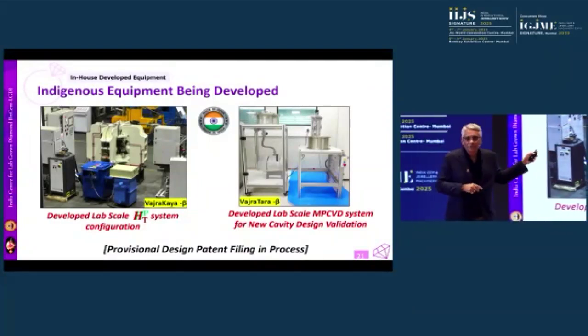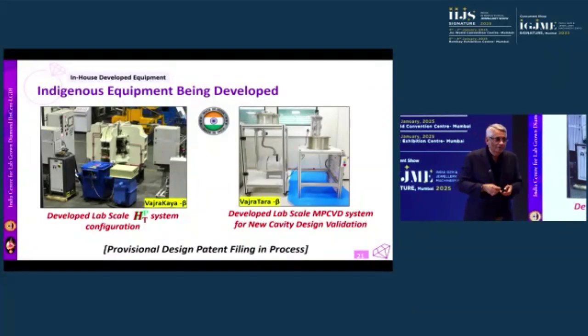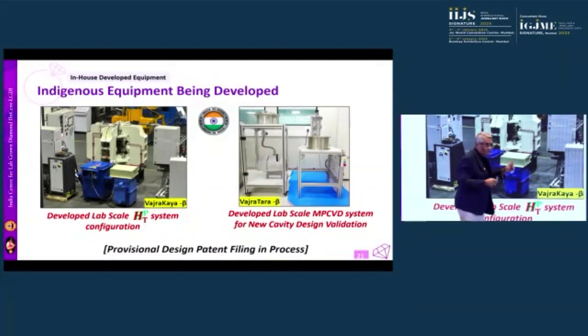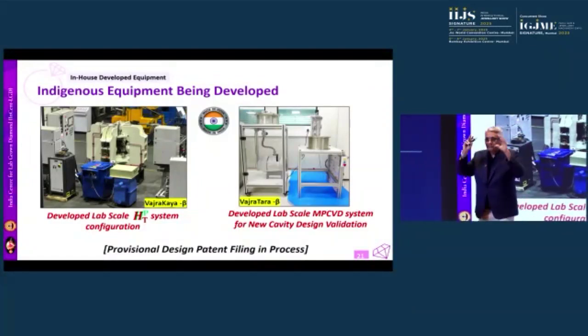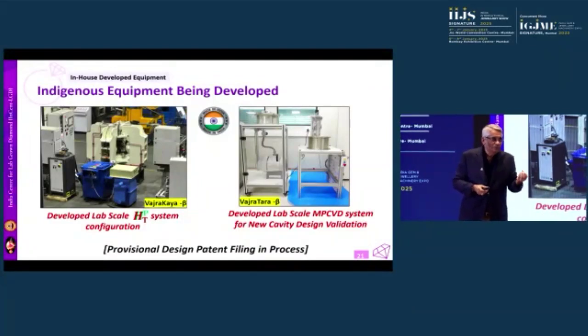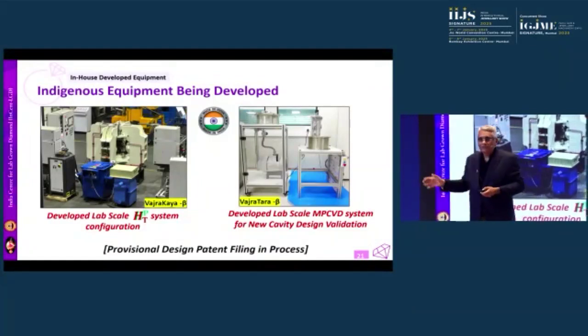And the most important component here, or bunch of components, is what sits inside the hydraulic system. There's a small block. It consists of about 15 different parts, carbon inside, some metallic powder, and it has to be heated under that pressure. That's called the cell, the supercell. We do not have the supercell technology also.